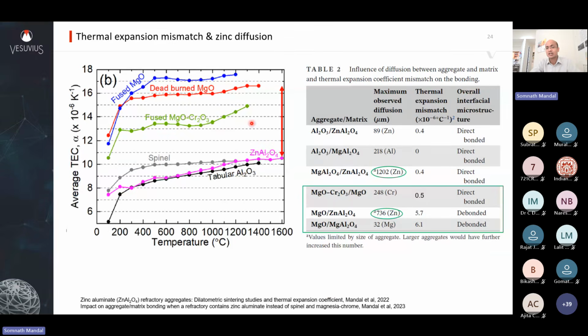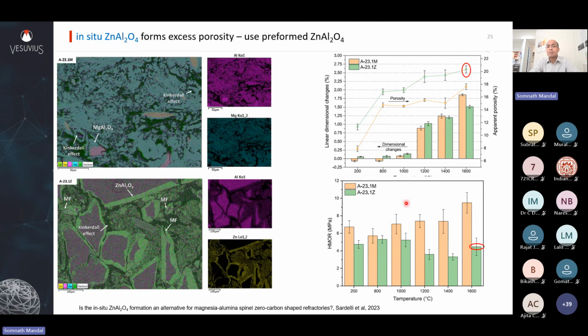And as I was saying earlier, the debonding happens due to the large thermal expansion coefficient difference between the magnesia aggregates and your zinc aluminate and spinel phases. And you get to counteract a little bit of that due to the high zinc interdiffusion into your magnesia aggregates. So you are better off with that. But just be mindful that you don't add zinc aluminate blindly.